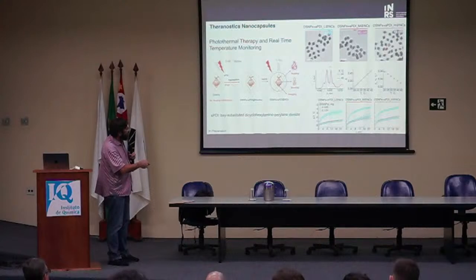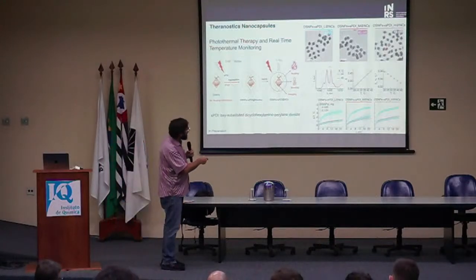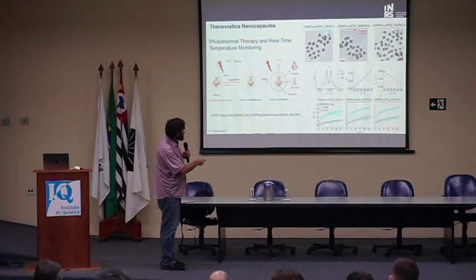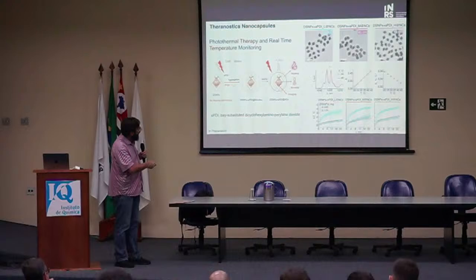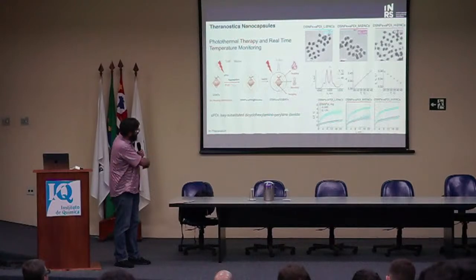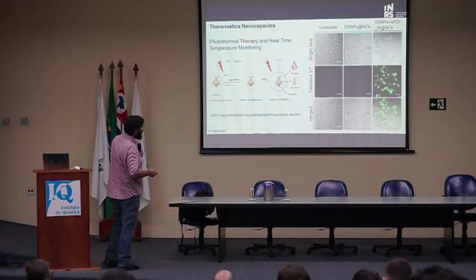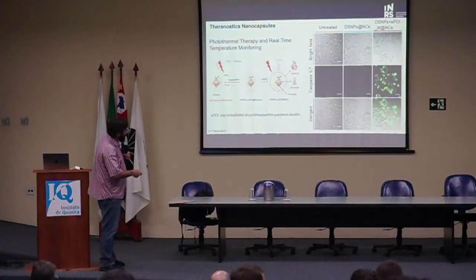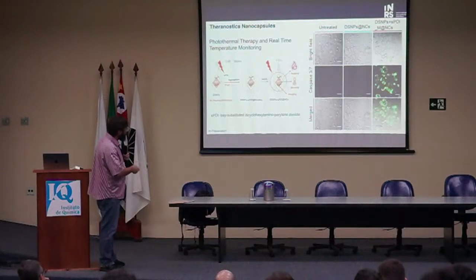So these are the nanoparticles inside this very thin, you can barely see it, but they're inside the capsule with the dye, and you can see that we can get heating. This is laser heating of the nanoparticle with the lutetium. Again, we have this temperature change, and we can control temperature in real time. We can monitor temperature in real time. Of course, the important part is here. We've stained the cells with calcein, and you see that when we have the dye and we're heating, then obviously they fluoresce because the dye fluoresces, and so we've induced apoptosis, so the cells die. So we can actually heat and monitor in real time.